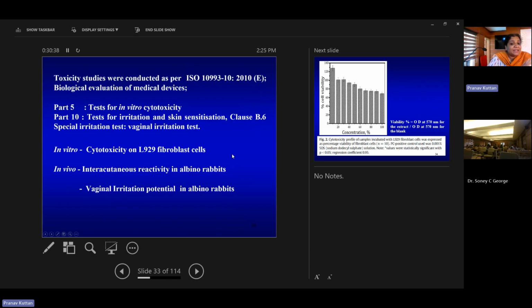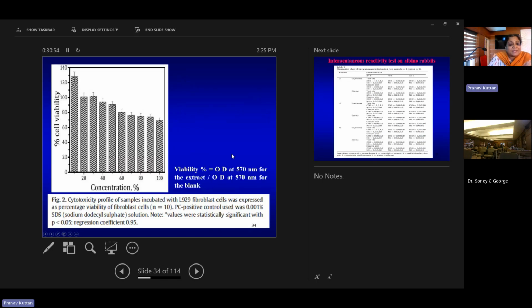As per the ISO standards, as I told before, different toxicity evaluations were done. First the in vitro cytotoxicity was done, followed by irritation and skin sensitization. In this particular case, since it's going to be used for developing diapers and sanitary napkins, vaginal irritation also was done in albino rabbits. This is the cytotoxicity evaluation, which was conducted using different dilutions of silver, and it was found that the cell viability is near 100%, indicating that it is not causing much cytotoxicity to the cell lines used.